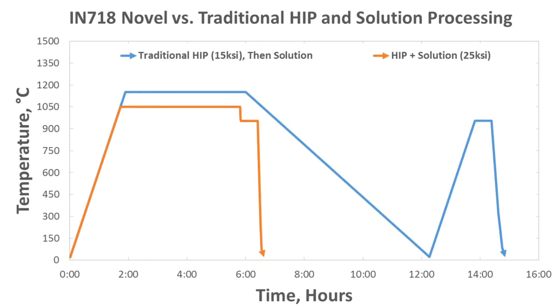But what I wanted to highlight here is you see the orange curve is rather different. So the process is actually combining both of these two effective goals into one cycle. And so there's a little bit of, not say trickery, but a little bit of unique processing there at the end of the HIP cycle. We like to call it a high pressure heat treatment cycle. But then you see we're actually cooling quickly at the end of that HIP cycle. And this equipment allows us to be able to do this sort of processing. And this is a novel approach, and it's something that we've had success with, which is why we're talking today.